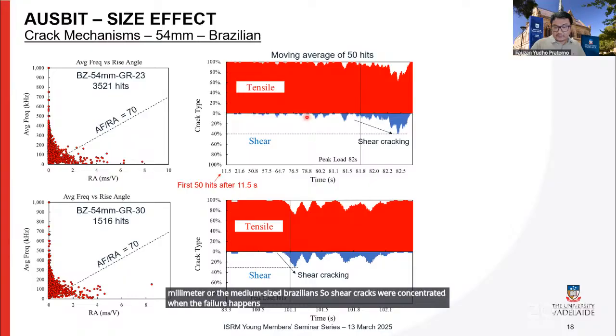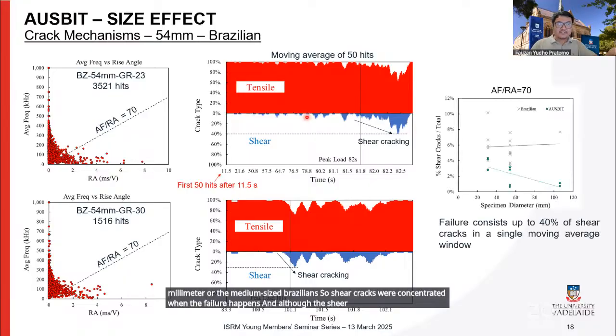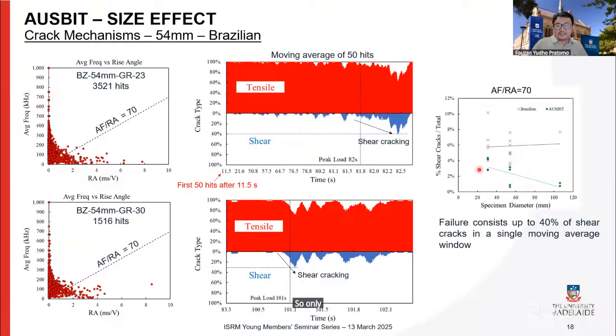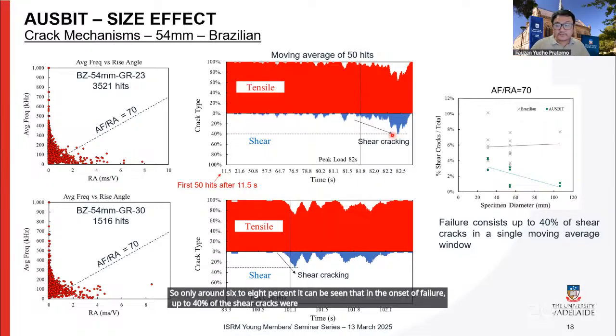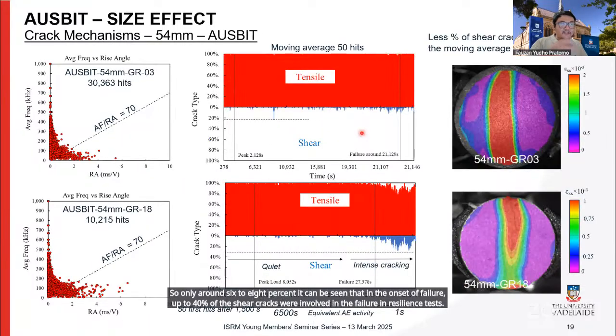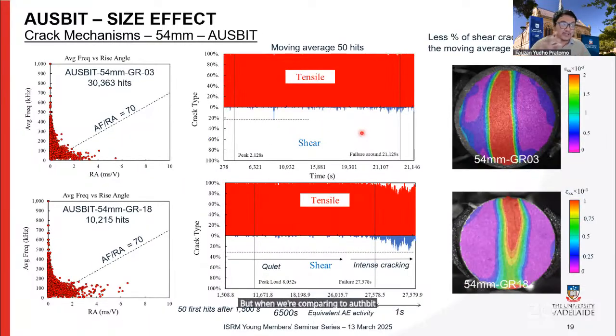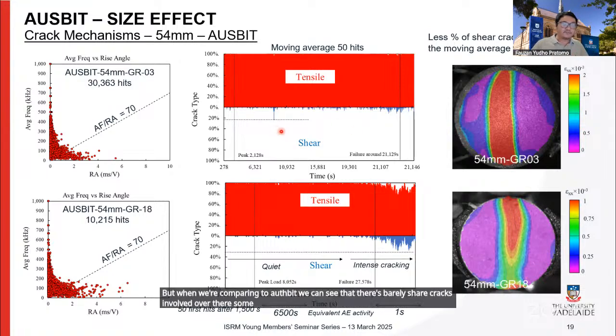And although the shear cracks seem insignificant in the previous slide, only around 6 to 8%, it can be seen that at the onset of failure, up to 40% of the shear cracks were involved in the failure in Brazilian tests. But when we're comparing to AUSBIT, we can see that there's barely any shear cracks involved. Although there are some sudden spikes, the values are not that significant compared to the Brazilian one, and clearly there are fewer shear cracks.